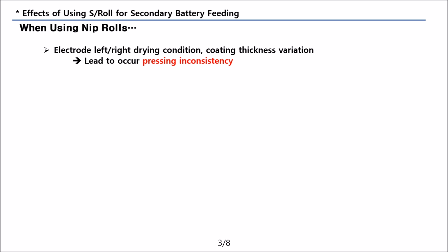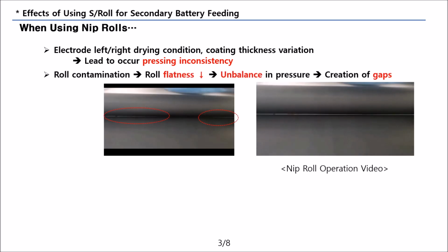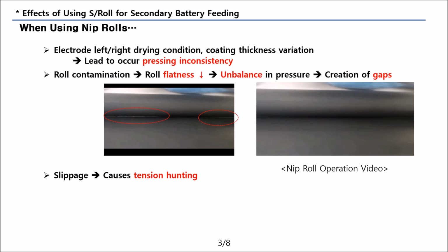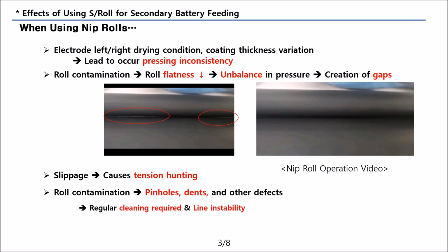Since the nip roll is made of rubber, it becomes contaminated if the electrode is undried or has uneven drying, leading to a deterioration in the nip roll's flatness. This causes an imbalance in the pressure applied to the electrode, creating gaps and resulting in slippage, which leads to tension hunting issues across the entire line. Such mismatches and contamination cause defects like pinholes and dents. Furthermore, regular cleaning and replacement to remove contaminants not only disrupt line operations, but also often lead to secondary damage to the nip roll during the cleaning process.